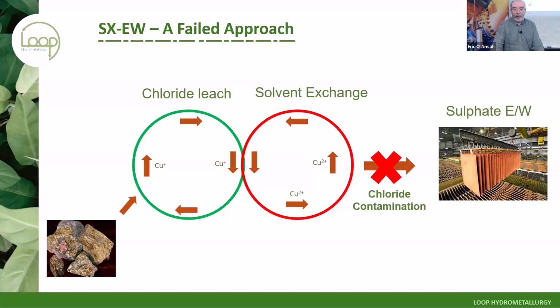In short, there are three major reasons why SXEW can't and shouldn't work. The first is simply chloride. If you're starting from a solution that is 6 molar chloride, or halides, let's just say halides, then SX simply cannot give you sufficient selectivity to avoid trace contamination of chloride in your sulfate, which completely messes up your sulfate electrowinning.